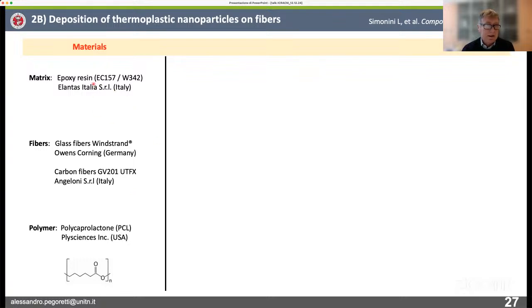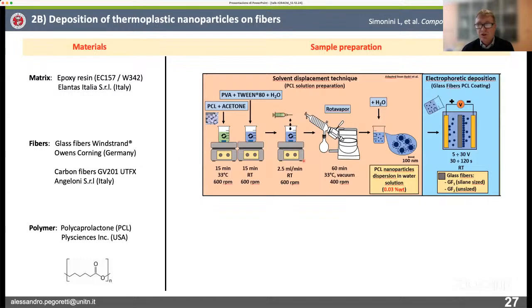We select a standard epoxy matrix and also glass and carbon fiber. So we use both type of fibers in these investigations. How did we coat the fiber with nanoparticles? Of course, we first have to generate a stable suspension of nanoparticles of polycaprolactone in water solution. And this took us some time because it is not easy to find the right ingredients in order to reach this condition to impede basically the coalescence of these very small particles. But at the end, we managed this.